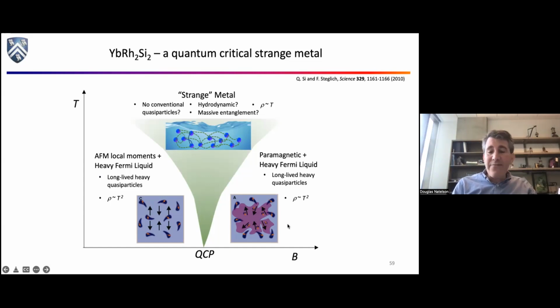Okay. At high values of magnetic field, you kill this antiferromagnetism, but the resistivity also goes like T squared. So you have a transition from a Fermi liquid to a different Fermi liquid. Okay. But above this transition point, the resistivity goes like T. And it's unclear what that means. It seems like the electrons are forming some big, complicated, highly entangled soup. At least that's the idea. And it's just not clear why you're getting rho going like T here.